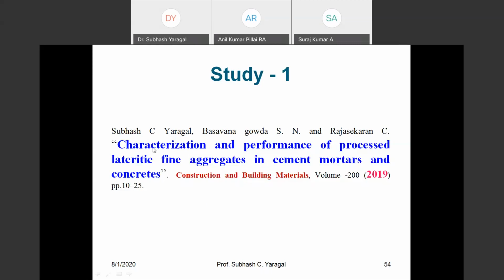So if you go for any level of replacement of your lateritic fine aggregate as a substitute to your river sand, you can do it to 100% replacement. That is what we are reporting here. Now, if you go for any concrete, you can straight away use the lateritic fine aggregates which have been characterized the way we have done. You get the strength same or more than that you would have got by using your river sand.